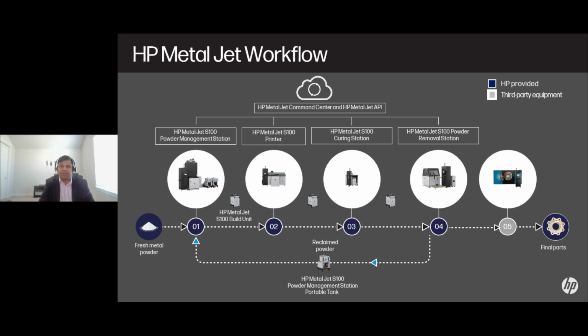But now you need the binder to solidify to give a strong part, which we call a green part. You take it off the printer and put it in the cure station, where you apply thermal energy for the glue to solidify. Once it's solidified, you have a strong green part that you can take out of the powder bed. All the unused powder is reclaimed and used for the next printing steps. The green part is cleaned in the automated depowdering station, which does 80 to 90% of the job of separating the green part from the loose powder.